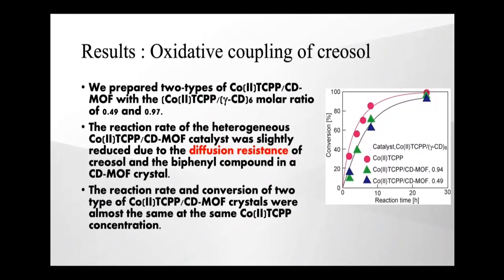Here is the result of the creosol coupling. We prepared two types of cobalt TCPP CDMOF with the cobalt TCPP to gamma-CD6 molar ratio of 0.49 and 0.97. The pink plot shown in the figure is the result of the homogeneous cobalt TCPP catalyst. The reaction rate of the heterogeneous cobalt TCPP CDMOF catalyst was slightly reduced compared to that of the homogeneous catalyst, because the diffusion resistance of creosol and the biphenyl compound in a CDMOF crystal was influenced. The reaction rate and conversion of the two types of cobalt TCPP CDMOF catalysts were almost the same at the same cobalt TCPP concentration.